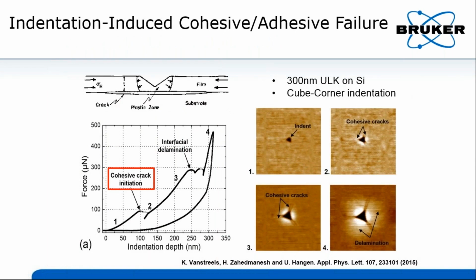Let's take the indentation method for adhesion to be the first high temperature application. The sample is an ultra low-k film on silicon, and a cube corner indenter was chosen to induce cohesive and adhesive failure. Similarly, popping events were picked up, and the force at popping events is detected as the critical load. Here we will focus on the cohesive failure at different temperature.